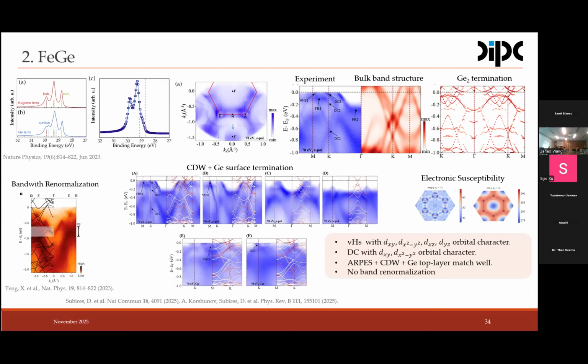I wouldn't say that we could have a perfect match, because the material at low temperature is composed of ordered dimers and ordered and disordered dimers, as I will show before. But we can actually describe the electronic band structure pretty well without assuming any bandwidth renormalization in the spectrum, right? So the message I want to convey here is that the electronic band structure of the iron germanium is not as much correlated as it was previously assumed.